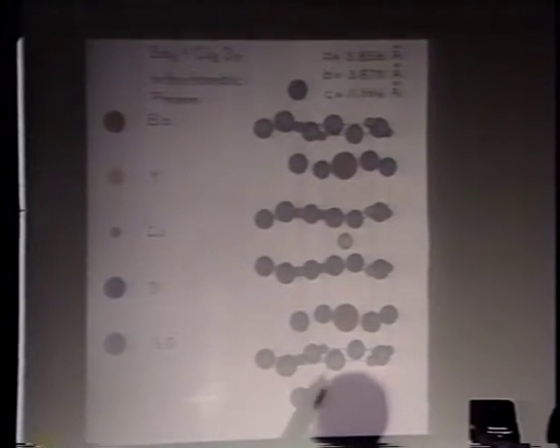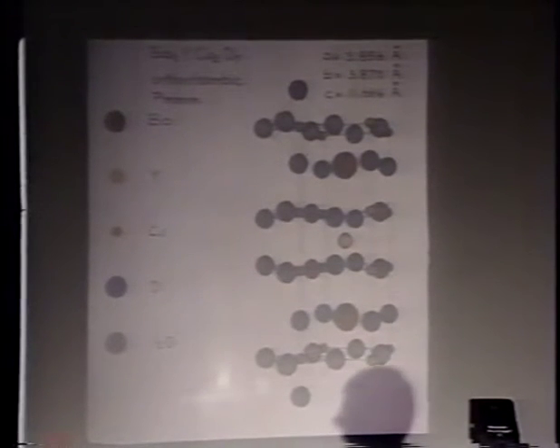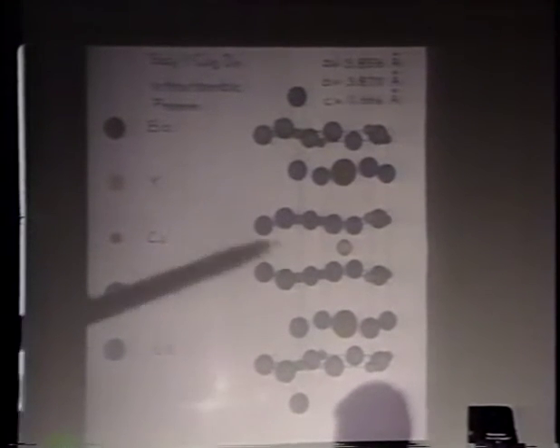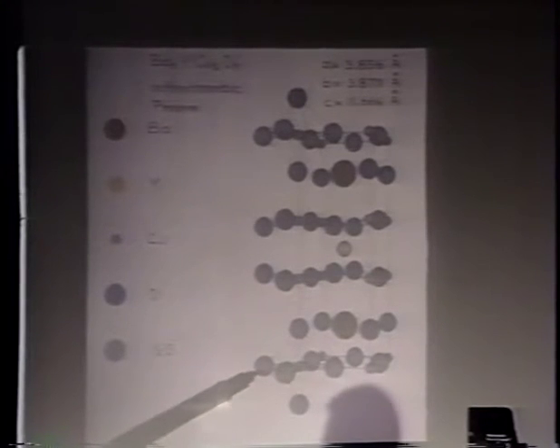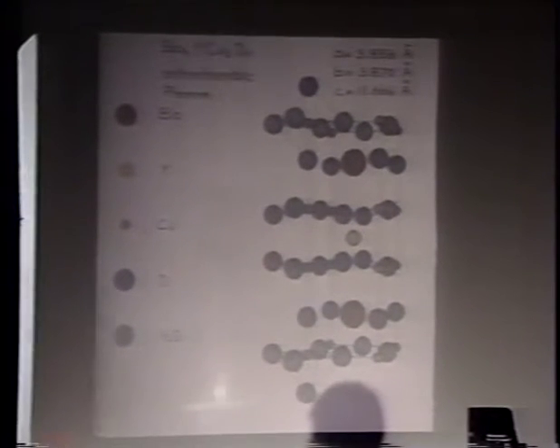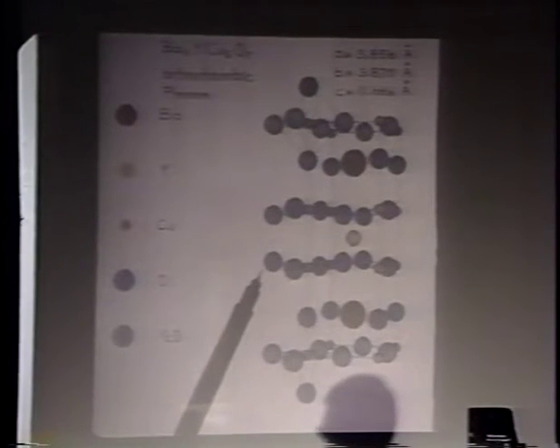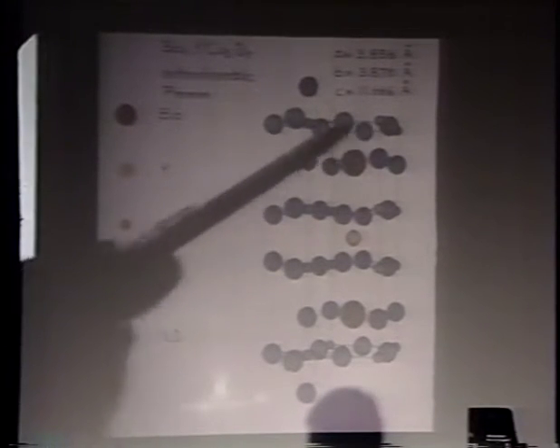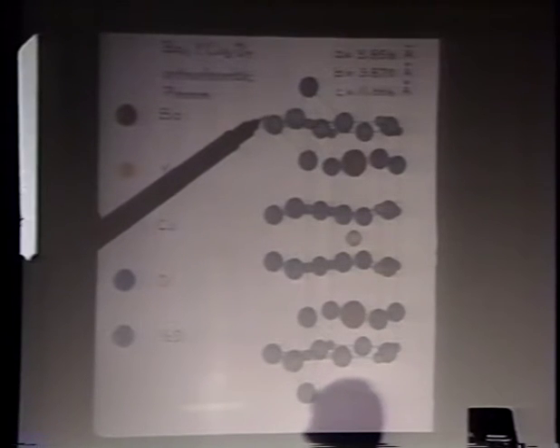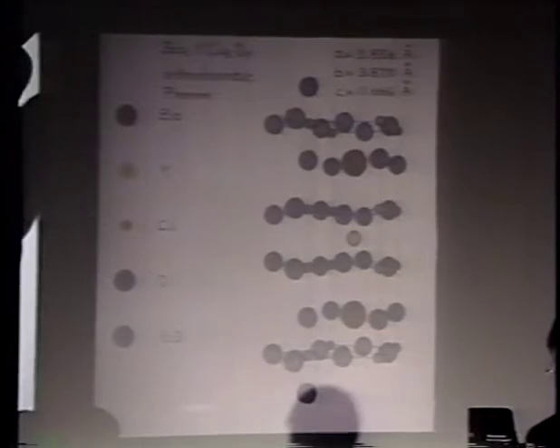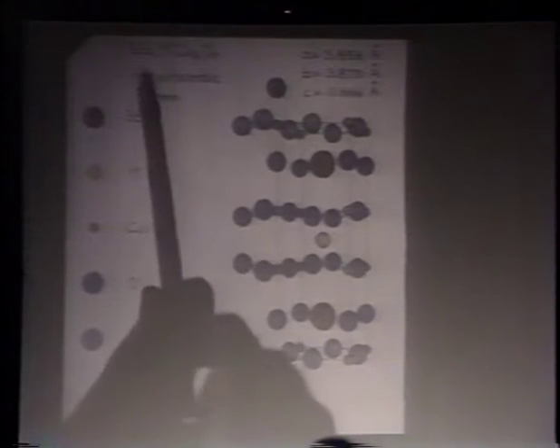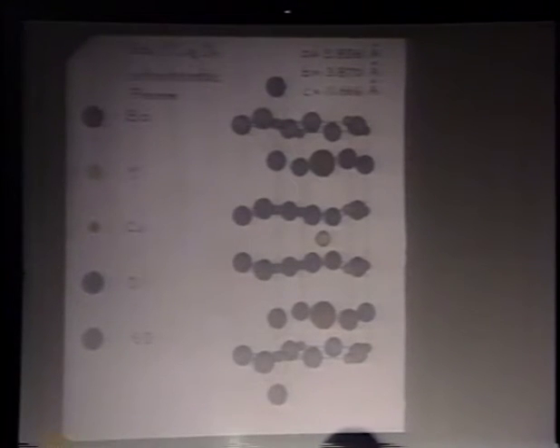I would like to point out that we start out from the perovskite, stack 3 layers of them. But since we do not have 9 but 7 oxygens, we have to take out 1 complete layer adjacent to the yttrium and 1/2 of the layer around here. So what we are left with is essentially 2 layers of copper oxygen, which are slightly buckled, and then in this layer, a random distribution of oxygen vacancies amounting to 1/2. That's the structure, starting from this insight and observing that the barium and the yttrium are regularly distributed. That's why we get 3 unit cells there. We have 3 times the A site occupied here.